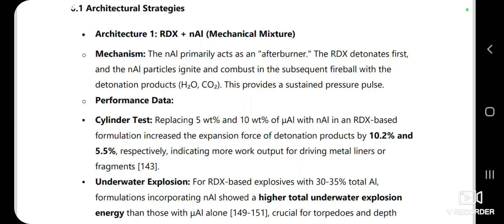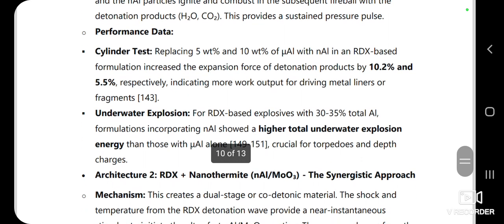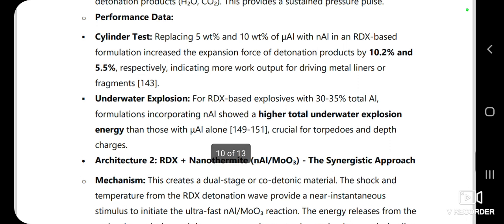The data confirms this: replacing just 5 to 10% of micron aluminium with nanoaluminium in RDX formulations increased expansion work by 5.5 to 10.2% in cylinder tests. For underwater explosives, that's critical for naval applications, nanoaluminium formulations showed higher total energy output.